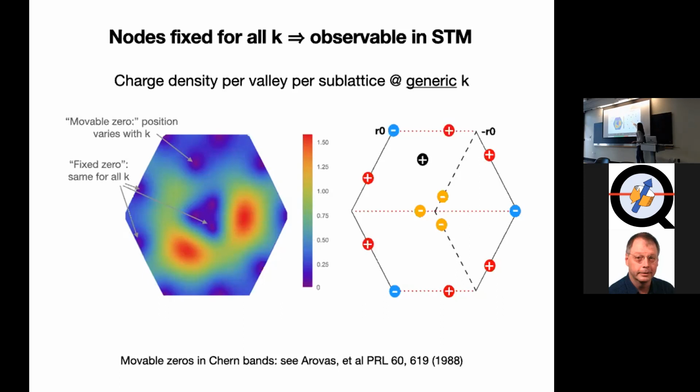As a consequence, there's a winding number of the net wave function, which is getting stronger as we get more of these zeros. At the first magic angle, there are no zeros in the middle. At the second, there are 3. At the third, there are 6. And so this winding gets enhanced. This made us think we should also be looking at the orbital magnetization, because the orbital magnetization is exactly coming from winding of wave functions.